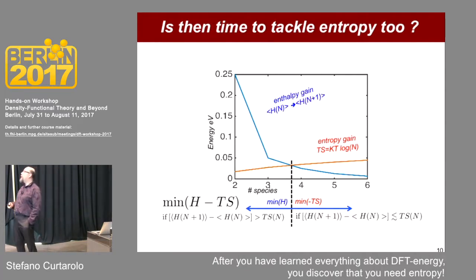That's because thermodynamics is convex, right? You always try to dig further and further. However, and that's the trick, at the same time, entropy is picking up. First, you don't know what this entropy is because we don't have the model. But even if you use the dumb model, which is the ideal model, the one that I used on the samarium hexaboride, which is x log x, is 1 over n log 1 over n. You have n species, so everything becomes log n. So in the ideal model, which tends to overestimate the entropy, you see that the entropy is monotonically increasing.